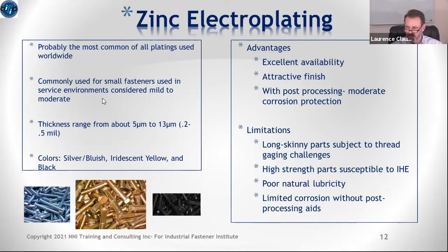Again, a lot of advantages. I already ticked down a number of those, but zinc electroplating also has its selection of limitations as well. Because of the chemistry of the way that the material deposits itself, if you have long, skinny parts, they become very vulnerable to heavy buildup at the ends of the part, which can then cause problems with thread gauging and things like that. So zinc electroplating, unfortunately, we might say, has far more problems with fitting parts together compared to something like hot dip galvanizing,